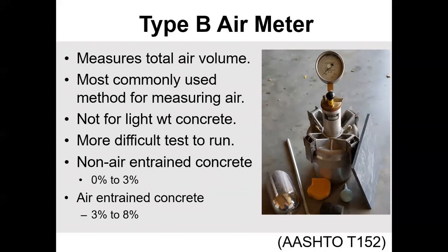Air is in concrete no matter what. Non-air-entrained concrete — where you don't add an air-entraining agent — will still have up to about 3% air from the mixing process, water, and materials. If you want to add an air-entraining agent for freeze-thaw resistance, people typically target 5, 6, or 6.5 to 7% air for air-entrained concrete.